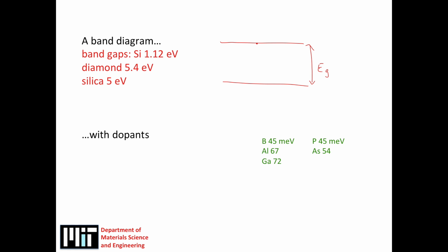And so those types of materials tend to have very, very low intrinsic carrier concentrations, and they will therefore have a very low intrinsic conductivity. However, if you do dope them, you can get conductivity, so there's no contradiction in having high band gap materials which are conductors.